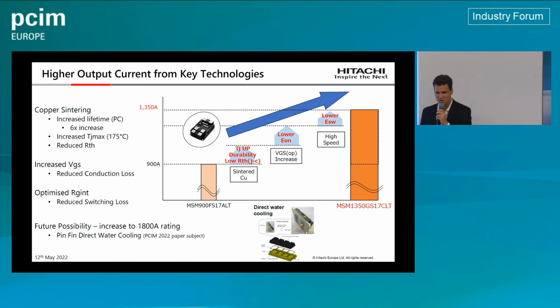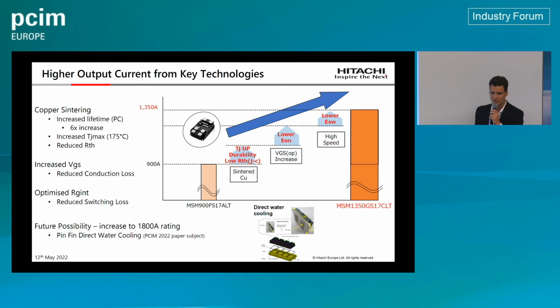So the switching transients we've heard about from our other presenters become much, much faster, and we see a roughly 35% reduction in switching losses. All of this together allows us to go from a 900 amp module in the same housing, same footprint, up to 1,350. And this really is rated to railway traction standards, so designed for very harsh operation with very high reliability and very high quality. You'll see a note down here.